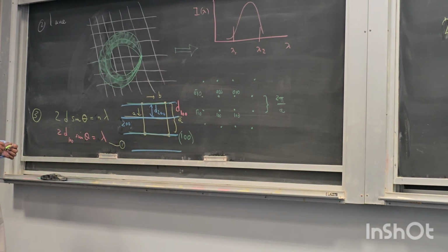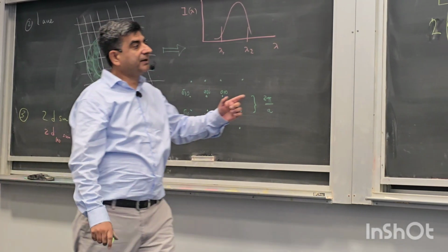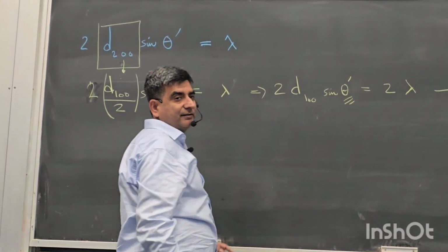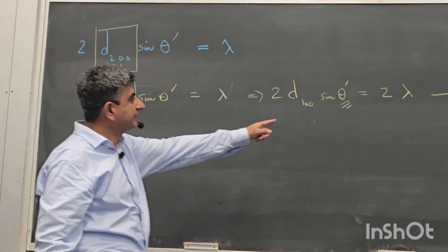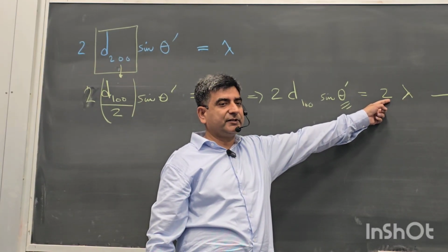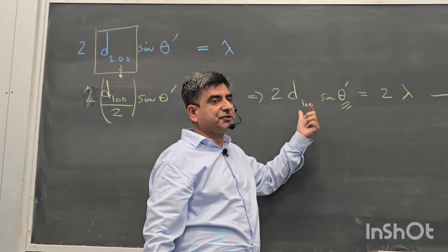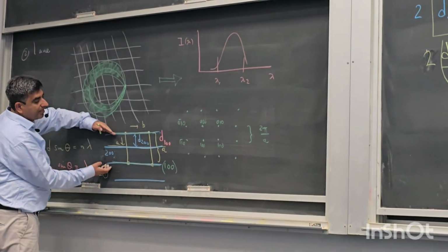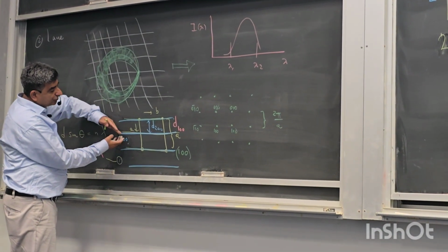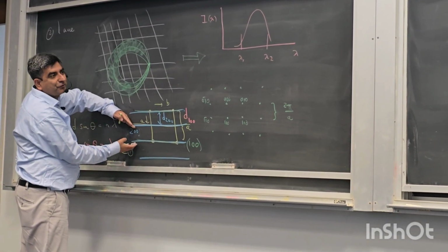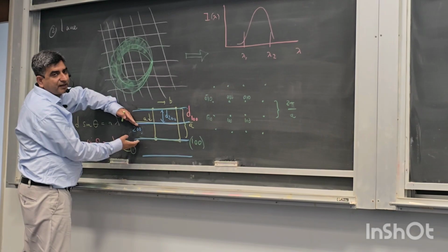Higher order reflections, this reflection by the way is going to occur at a different theta, right? Because one of the formulas has 1 here, the other has 2 here. So higher order reflections from these planes, which are equal to first order reflections from the planes in between, are going to necessarily occur at different angles.